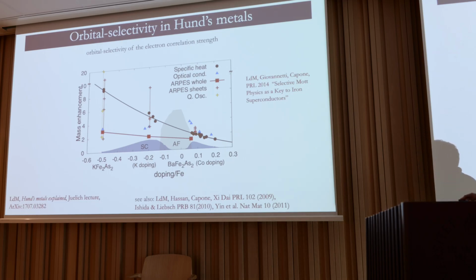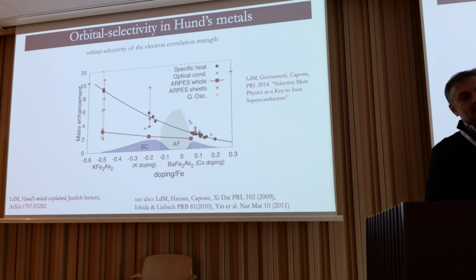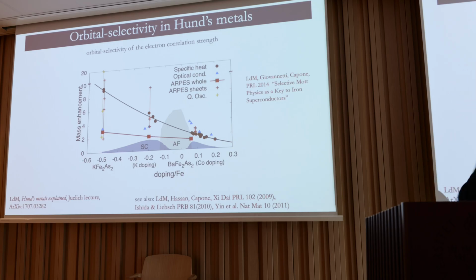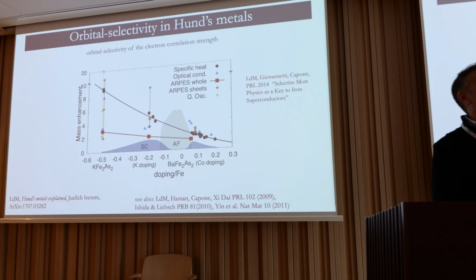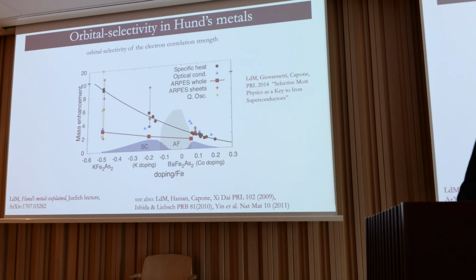This is nicely seen in many experiments. These black points are the same Sommerfeld coefficient that go up in the family, so I won't mention them again. But if you look at other probes for mass enhancement, like the optical conductivity, you see a story which is much less impressive—they sort of saturate. This is due to the fact that strongly correlated and weakly correlated electrons coexist at the Fermi level in these compounds. Depending on which probe you look at, you see a probe dominated by heavy electrons or by light electrons. The specific heat is dominated by heavy electrons, while the optics, the transport, is dominated by light electrons.